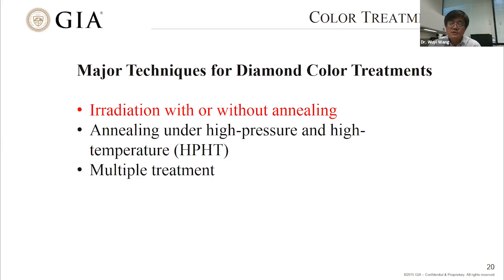So the first one has a long history, started almost a century ago: irradiation with or without annealing. We put a diamond under a very high energy beam to be irradiated, and some stones could be heated after the irradiation. Some may not necessarily be heated, depending on what color we want.